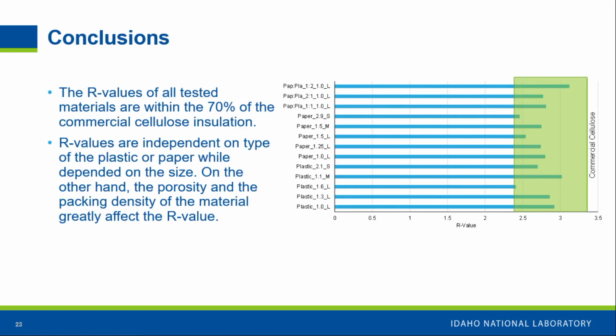So in conclusion, that's the result we found: the R value of the cellulose we measured about 3.35-ish, and the other MSW, plastic, and paper fractions, all of them are within the 70% band. So that means we are getting something not better than cellulose definitely, but most likely compatible with the cellulose. And we saw that they are highly dependent on the porosity of the structure and how we are packing the material. And this is just the beginning.